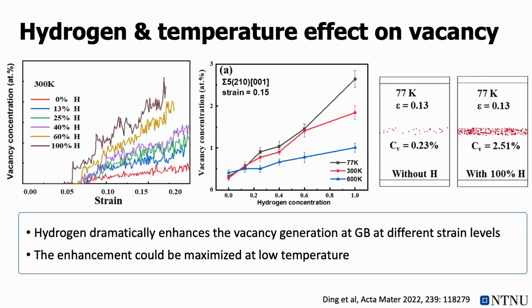And of course, we can also see further how the hydrogen concentration influences the vacancy concentration, and also the temperature influence on the vacancy behavior. Let's see here, when we increase the hydrogen concentration, the plasticity onset, of course, changes with the hydrogen concentration. And also the vacancy concentration increases dramatically with the hydrogen concentration increase. And this behavior becomes more pronounced at lower temperature, mostly because lower temperature limits the thermal vibration of individual atoms in their positions. And we see that at a low temperature, the vacancy concentration with hydrogen is almost 10 times higher than without hydrogen.